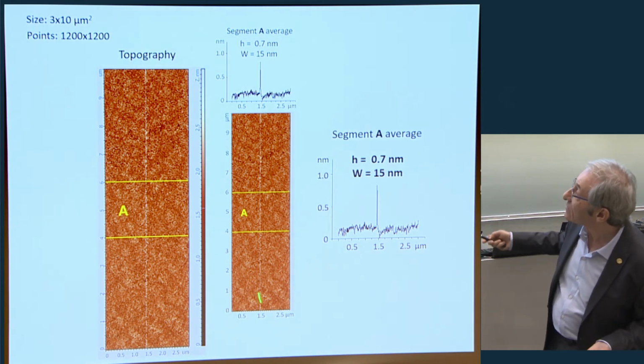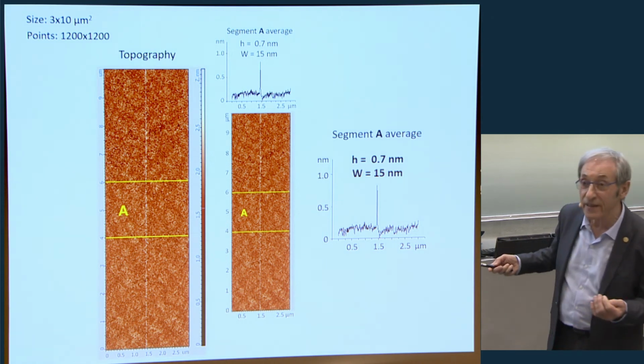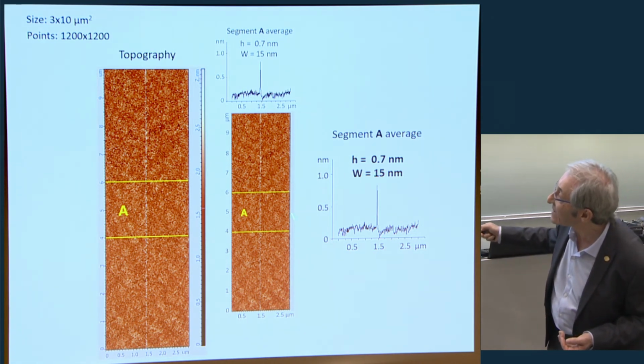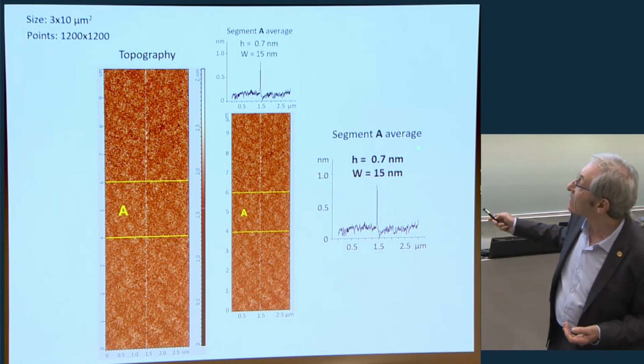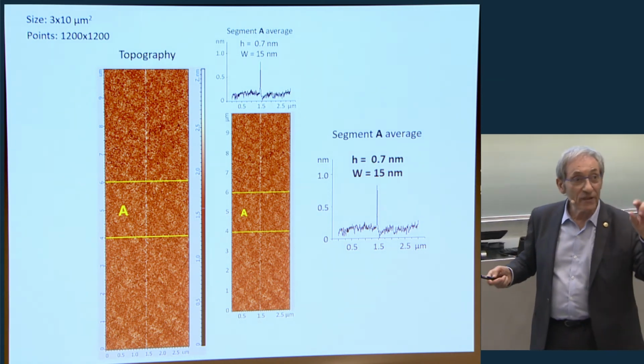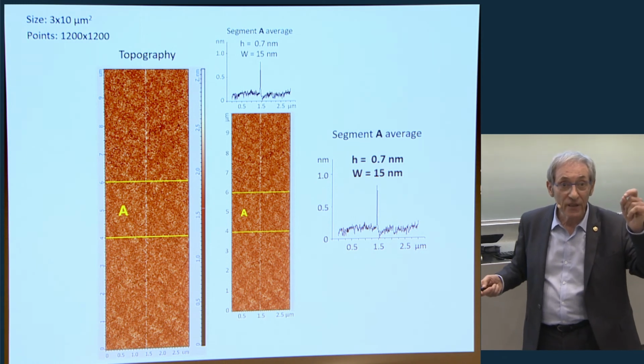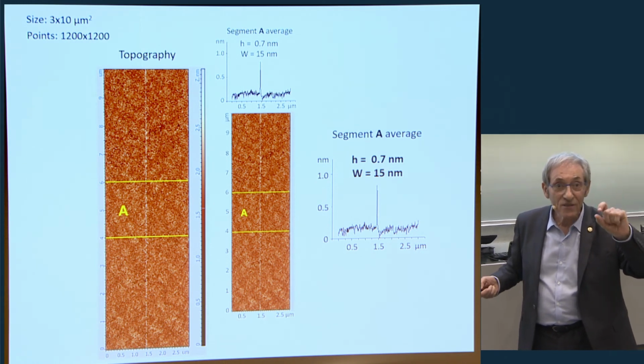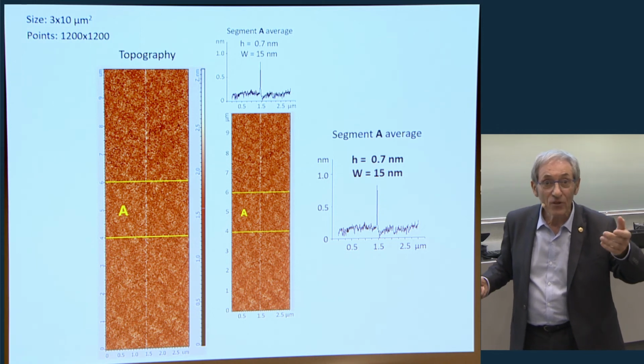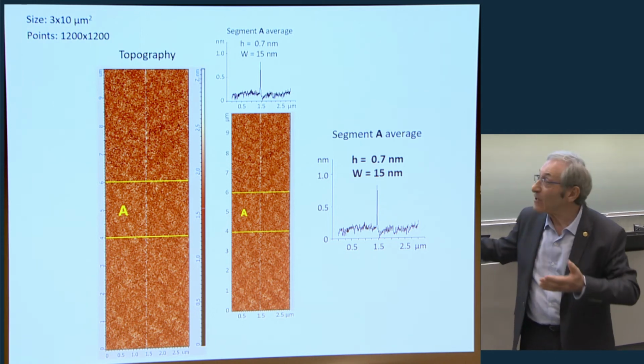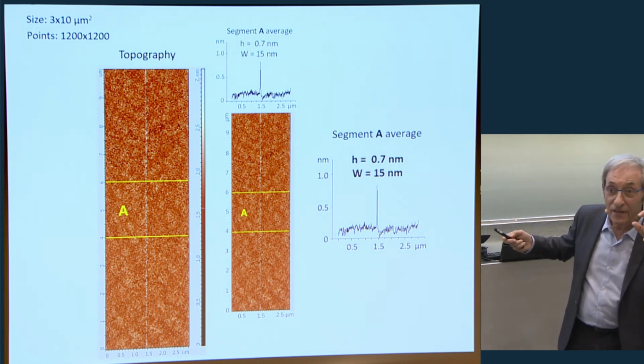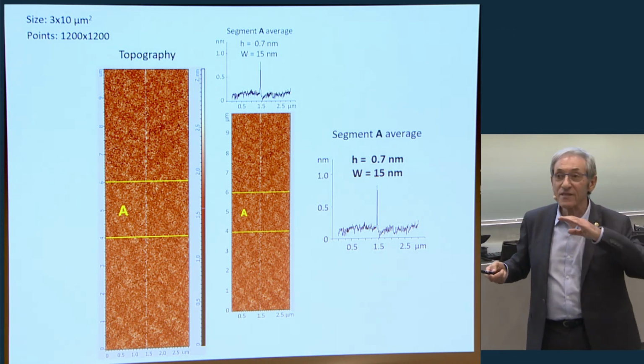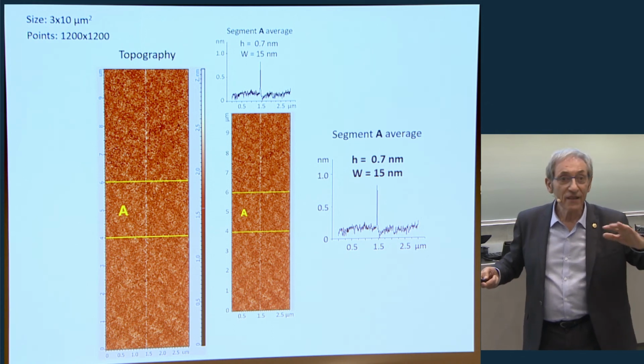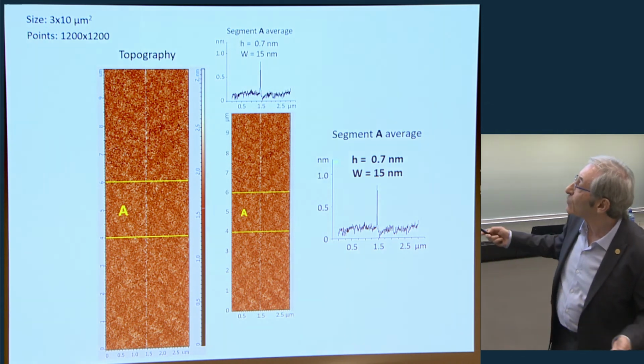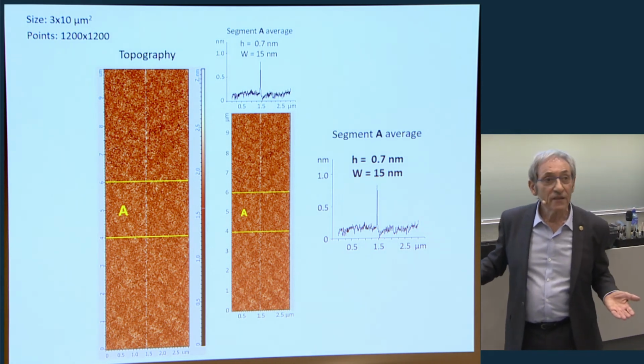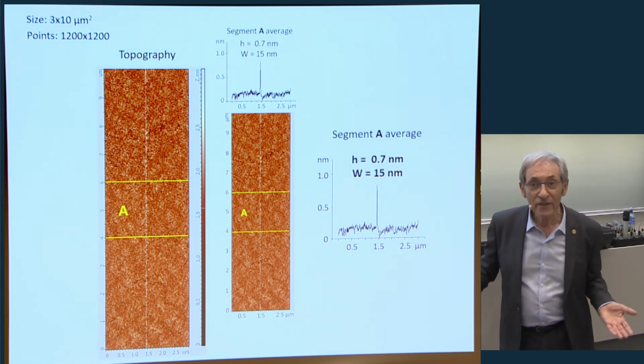We have such a composite nanowire that has a height, this is the average of this segment, of less than 1 nanometer. This contains both PVA and silver. We don't know yet what is the thickness of the silver and what is that of PVA, because this research is underway. But of course, it's very, very little. We believe that we are talking about a single layer of silver, just like graphene. And the width is about 15 nanometers. And it is an exceptional conductor.